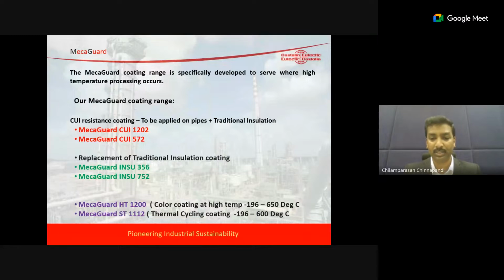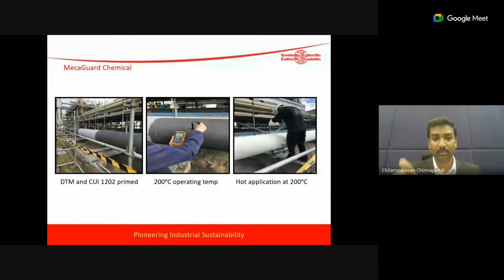And we have the color coatings also, from minus 196 to plus 650 degrees. So for any color coating to be done where normal paint gets faded, this coating will not fade up to 650 degrees. It can be used, and you can change the colors as per your RAL. We can manufacture and give you a customized color product.